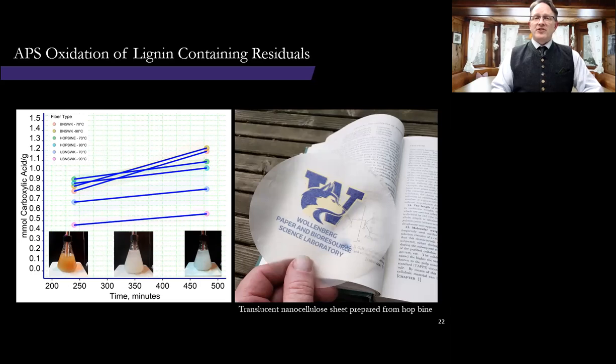Finally, I produced a film of the hop bine NFC. However, due to its really poor drainability, and the large number of fibers required to make the film, it really isn't very feasible. It's great to demonstrate the transparency of the film. You can see the book below the film. So instead of examining films, in part 2, we chose to use an engineered NFC fiber as a reinforcement for paper fibers in this work.